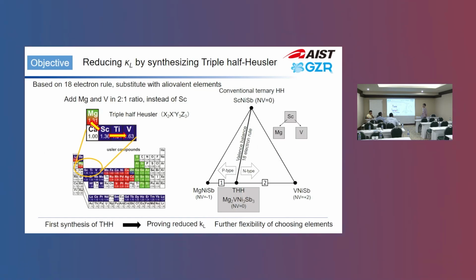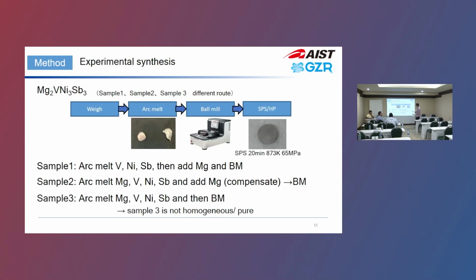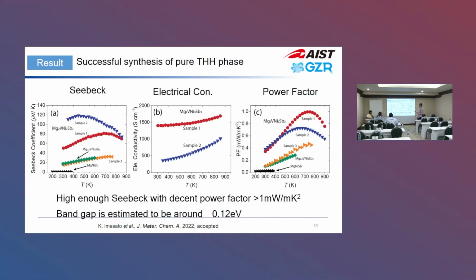And for the second question: you said that you made a triple Half-Heusler, which basically starts from mixing N-type and P-type, right? So how do you know how much N-type or P-type to put in to balance? Because one of them has P-type conduction, the other N-type. Yeah, we are just trying to count up the electrons. Usually, they aim for an 18 electron count. For ternary compounds, magnesium is 1 electron down, right? And vanadium is 2 electrons up. So if you combine them in a 2:1 ratio, it's going to be closer to 18, and it should have intrinsic semiconducting behavior. But this time it's P-type, probably because of slight magnesium vacancy formation or something.